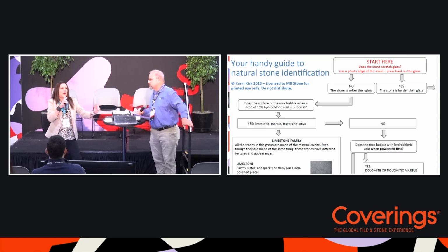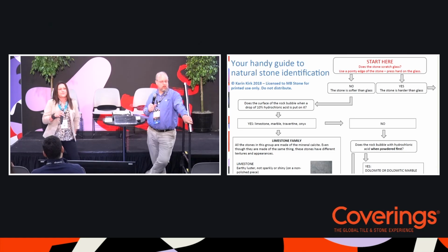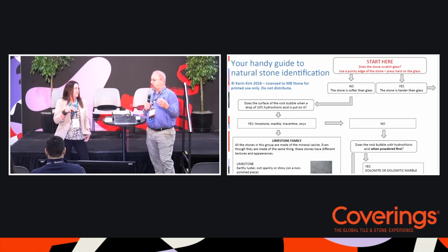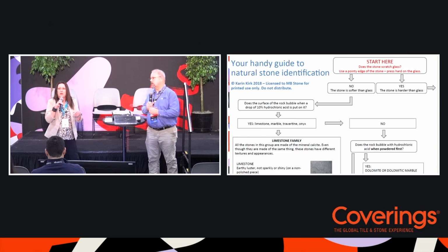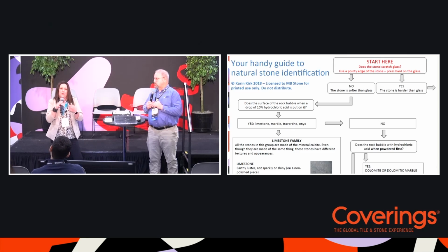That's why I like the water test. That's why I think it's so important. Because if water sits on this stone for 10 minutes and nothing happens, it doesn't turn darker, nothing is absorbed, it doesn't need to be sealed. It's not absorbing water, so it's not going to absorb that sealer. Any other questions? Quick clarification, Denise, because you mentioned the water test earlier. That's letting the water sit on the stone for 10 minutes? Yeah, so you can see if it discolors or darkens. If it turns darker, it's absorbed, and it does need to be sealed. It is absorbent. If you let it sit there, you wipe the water away, there's no mark, you can't tell where it was, it's not absorbent.